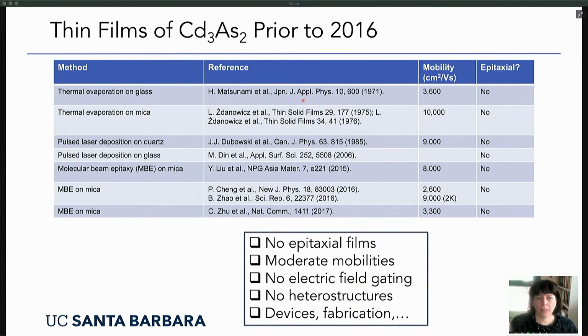And so basically there were no epitaxial films in 2016. They were often put on substrates like glass or quartz or mica, where you would not expect an epitaxial film. But despite this, the mobilities were actually quite high. So these are room temperature mobilities here, and for non-epitaxial polycrystalline films, these are actually quite respectable. But compared with what we would expect from cadmium arsenide, these were moderate mobilities. There were no electric field gating studies, no heterostructures, no devices or device fabrication beyond measuring mobilities. So this is where things stood.